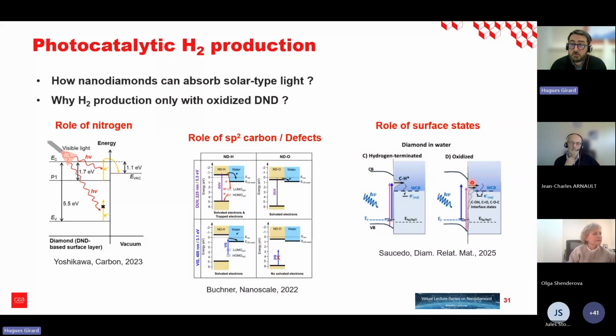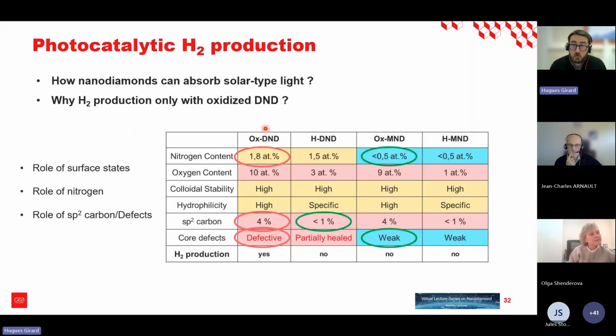If you look at the literature, and Jean-Charles already explained that, you can see that finally there is a role of nitrogen, which can be important to help absorb the light, also sp2 carbon and defects inside the detonation nanodiamonds. And more recently, the Hamers team published a paper in which they showed that even with oxidized bulk diamond, you may have some solvated electrons emitted in water, even for sub-bandgap wavelength. And so if you look at all the characterization of all the types of nanodiamonds, finally what you see is that the oxidized detonation nanodiamonds may gather all these properties at the same time: I mean high nitrogen content, presence of sp2 carbon, and a very defective core. So this is so far what we think is at the origin of the production of photocatalytic hydrogen in presence of these detonation nanodiamonds.